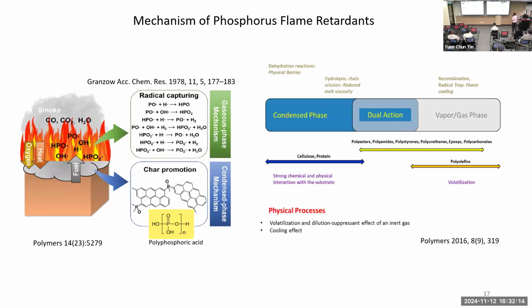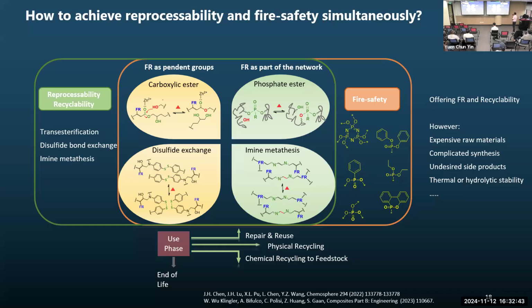But one has to understand the way the phosphorus flame retardants work depends mostly on the polymer which you're using. So if you have a hydroxyl containing polymer, the phosphorus normally does the dehydration reaction and you form char. And if you have an oxygen-free polymer like polyolefins, the flame retardant action of phosphorus is more in the gas phase. Okay. So coming back,